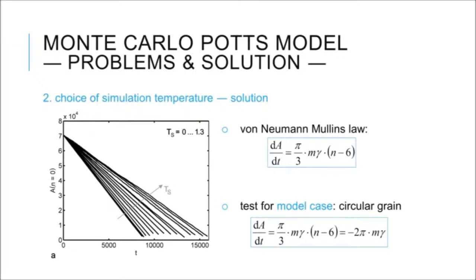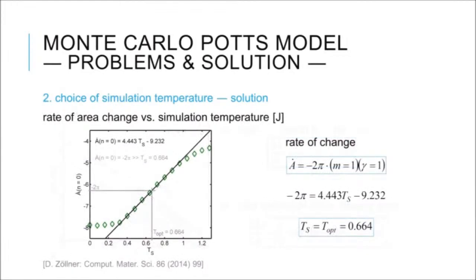Now I can plot the slopes that you can see here as a function of the simulation temperature. And the result? Well, we see that apparently the area change rate is indeed a function of the simulation temperature, and only at one point do we get that the slope equals minus 2 pi. This is precisely my optimal temperature of 0.664.